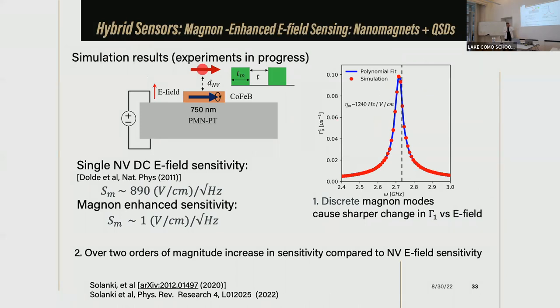And you can make a sensor based on this with record high sensitivity to electrical field, because in that case, you apply the electrical field and change the spin relaxation, which we measure optically. But I could reverse the problem and ask what electrical field caused that particular change in the relaxation rate, and use it as a sensor. It turns out that this type of sensor would be, by two orders of magnitude, the best sensor existing. Something which we hope to demonstrate soon.